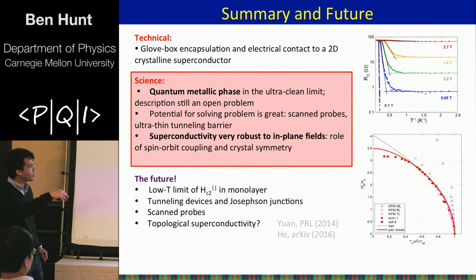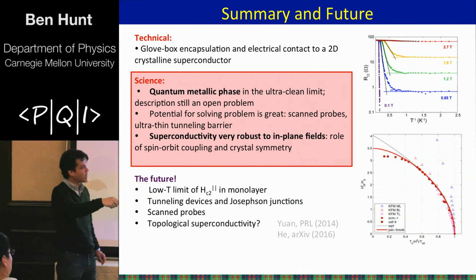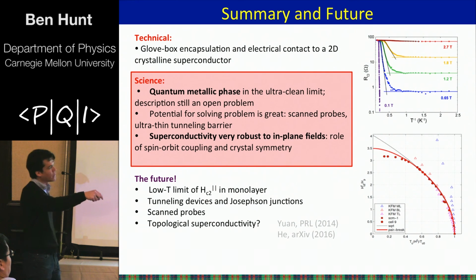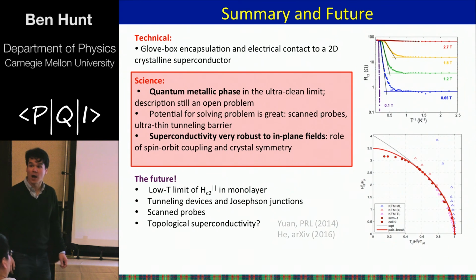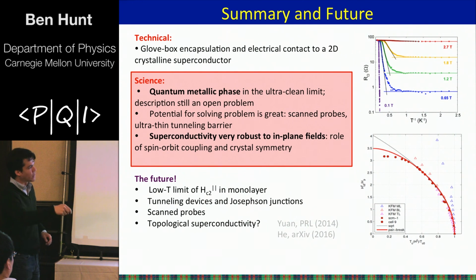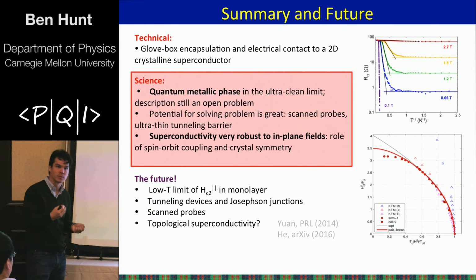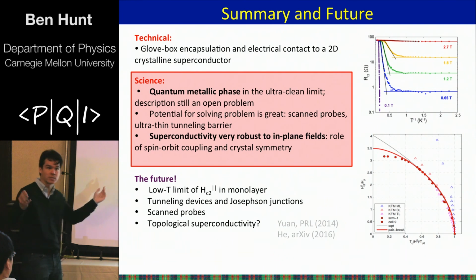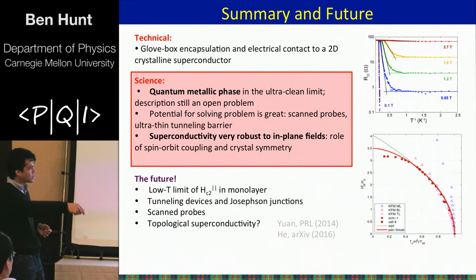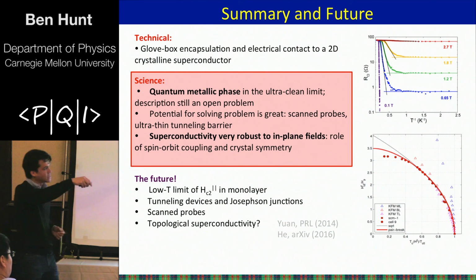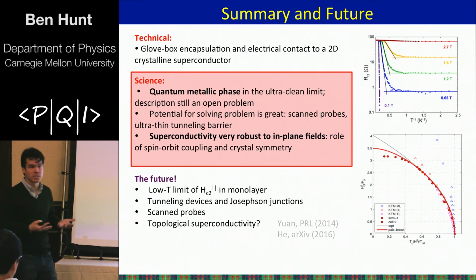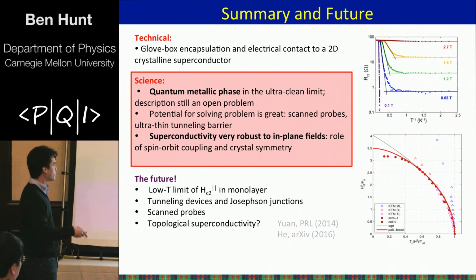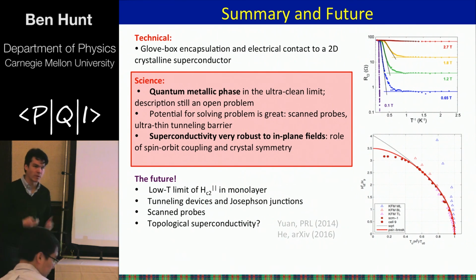In the future, for the in-plane fields, there's a number of ideas. One was alluded to in the last talk, that it's possible that in the superconducting phase at very, very high magnetic fields, you might see one of these FFLO, Fulde-Ferrell-Larkin-Ovchinnikov phases. For the out-of-plane field in the quantum metallic state, we'd like to look at it with tunneling experiments, in which we might be able to see what the spectrum looks like, see if it looks like a pseudogap-like phase, like in the high Tcs. And there are some very interesting ideas that in this kind of high Zeeman energy superconducting phase, we might be able to see some form of topological superconductivity. So that's basically it. Thank you very much for your attention.